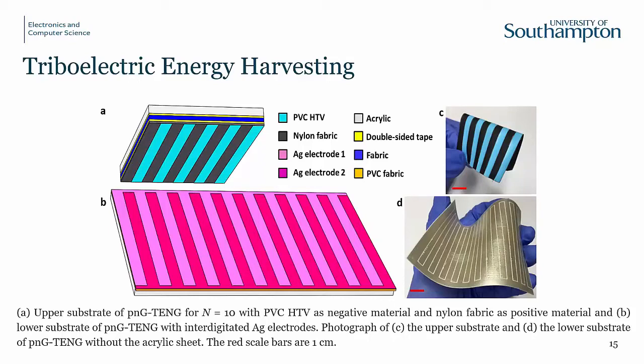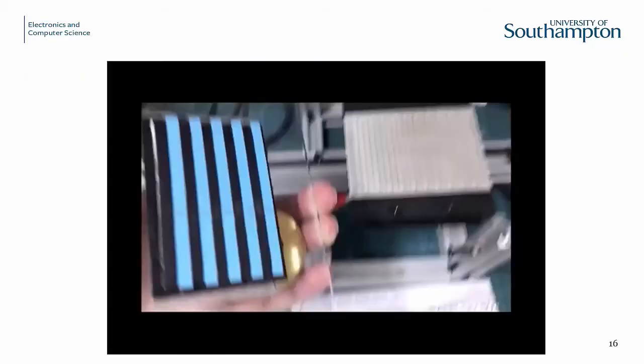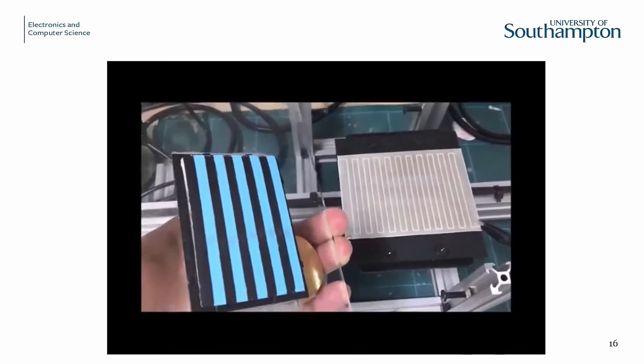So you have materials with a positive affinity that will become positively charged, or negatively charged, depending on the material you're rubbing them with. And here we're combining positive and negative materials, so this is nylon and PVC, and then combining that with an IDT textile electrode here, and when you rub these, the top surface along here, basically you generate electrical energy, which should be shown in this video here.